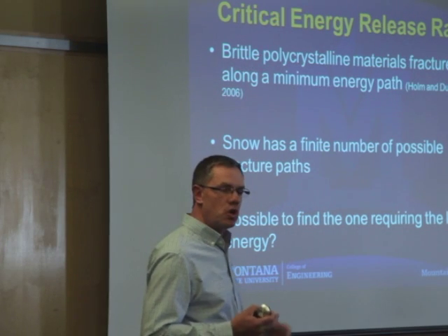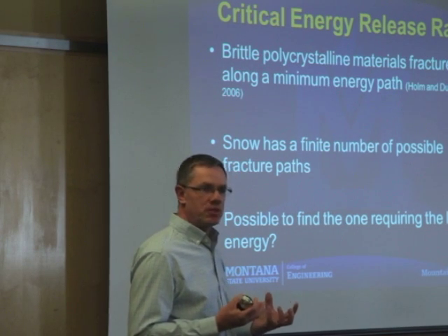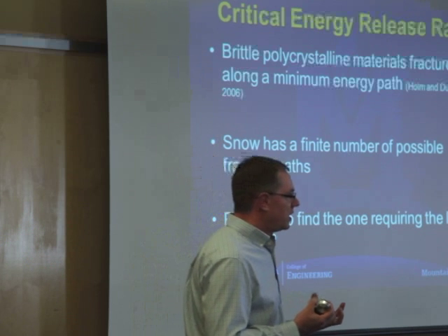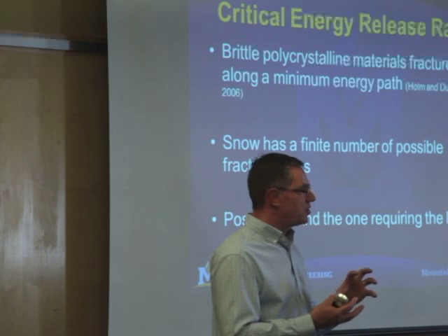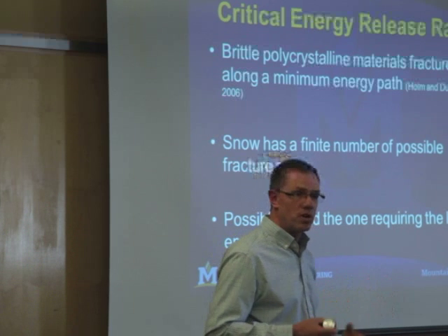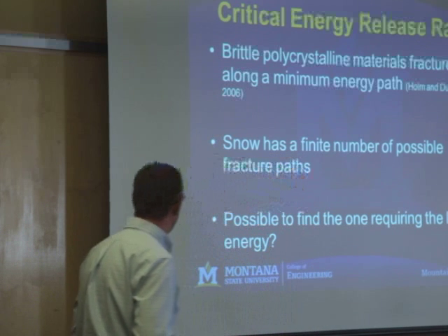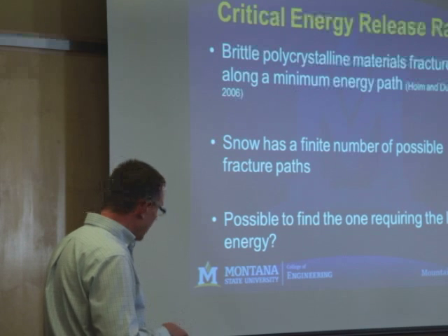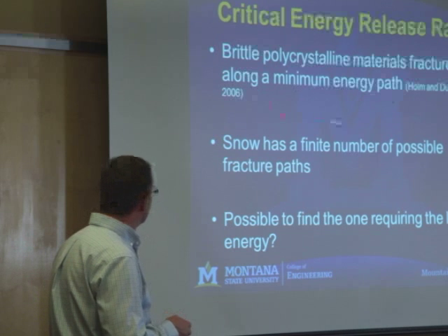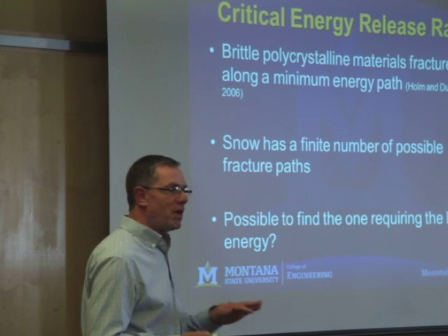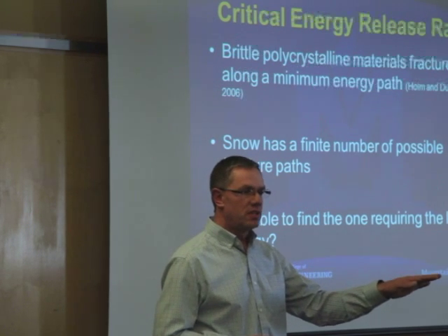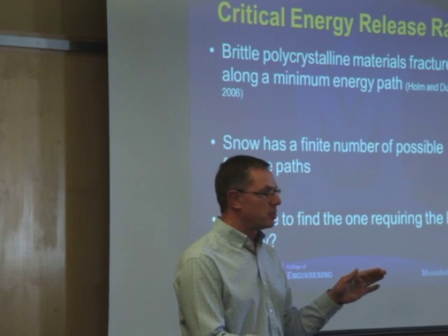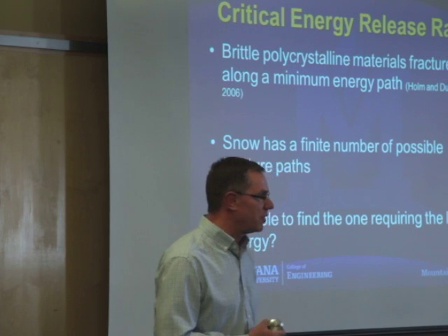Okay? And we've gone and looked at other fields. Snow is a polycrystalline material, right? Ice is a crystal. And there are other fields where they've looked at these polycrystalline type materials and looked at this problem. Ceramics is one of them. So we started looking at some of that, and what we find in fracture, and it's well documented, is that there is a path that's going to go through that microstructure that requires the least amount of energy for that fracture to propagate.